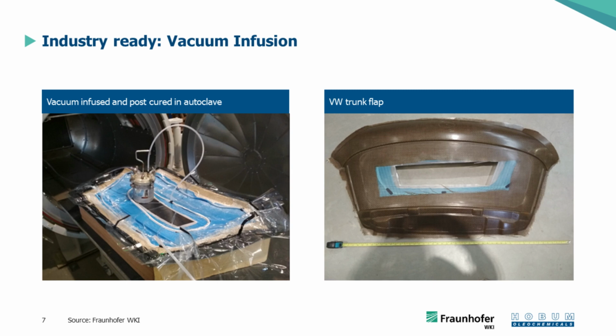The other method applied and used in industry is the vacuum infusion. Instead of pumping inside, you apply a vacuum. You have only one mold, and you put a film on top of the fabric, and you vacuumize, and then suck in the A and B component of the resin, which is previously mixed, and then you put the whole thing in an autoclave and cure the product. And on the right side, you can see quite complicated structures are possible. This is a trunk flap of a Volkswagen Scirocco.